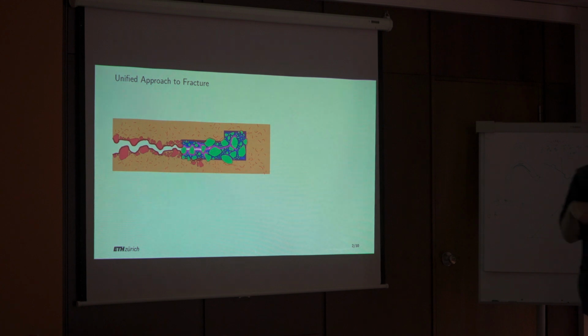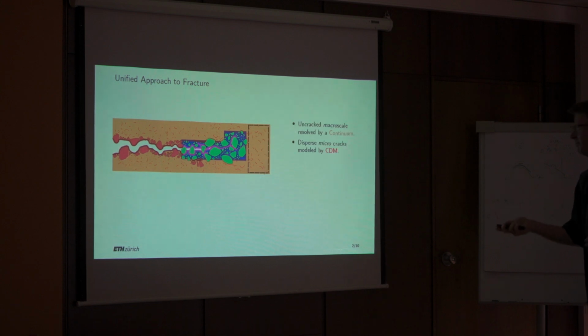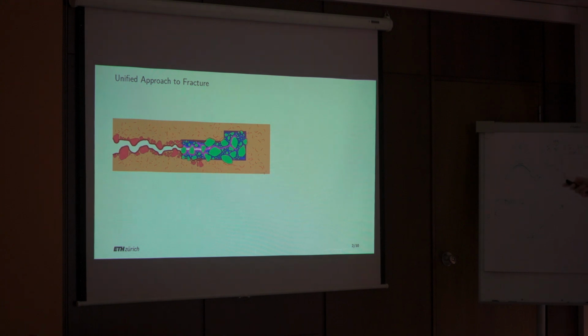In my thesis, I'm developing a new method which is able to capture this whole process and tie it through the entire life of the crack to the same microstructure. It initially begins in the continuum, where in the uncracked domain the material is resolved as a continuum, and the microcracks in it are modeled by a continuum damage model.